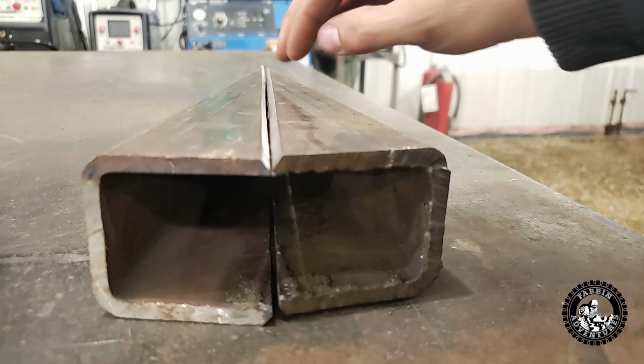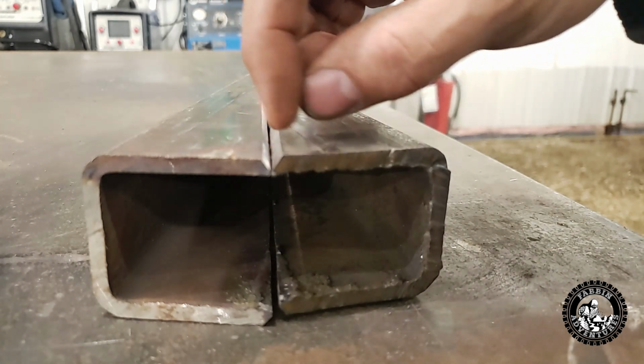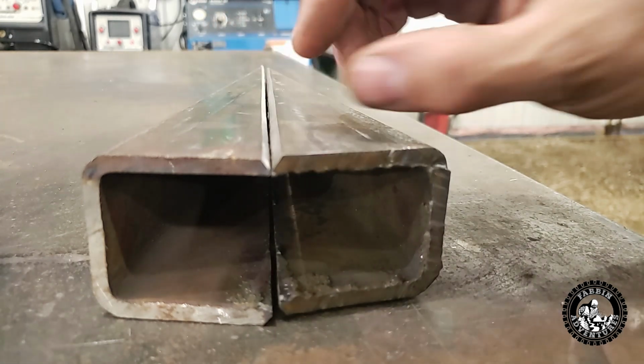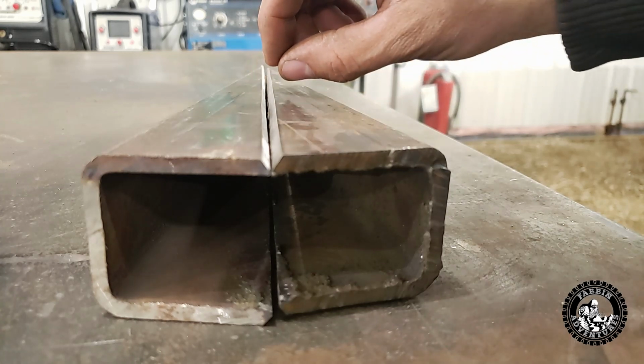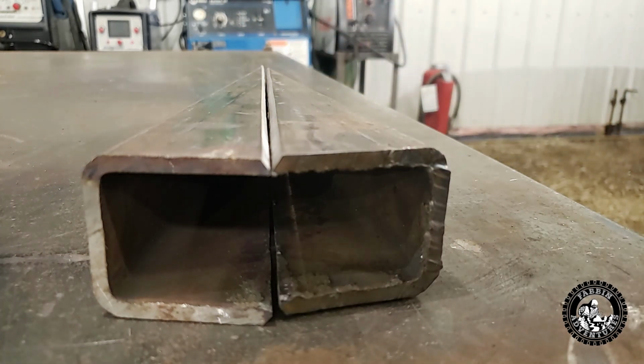You could grind that off flush and it'll be a solid bead right down to the bottom of these welds. If you don't grind those edges out, you're only going to get partial penetration through, and then when you grind it off flush, you're only going to have a very thin little bead, unless you really crank your welder up. But this is the correct way to do it and the better way to do it.